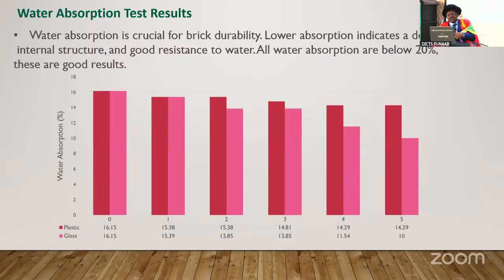When we look at the water absorption of all the samples, water absorption is critical for brick durability. Low absorption indicates a denser internal structure and good resistance to water. All water absorption are below 20%. These are very good. It shows that in water absorption, all of them perform well.